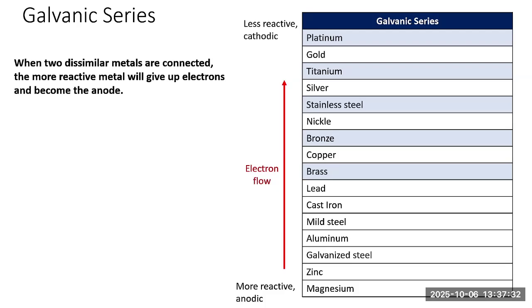And here's an example here, an aluminum fitting attached to a copper pipe. And I'm going to circle the aluminum here and the copper. So what do you think is going to happen here if I connect those two? Well, the aluminum is going to give up electrons and it's going to flow to the copper. So aluminum is going to deteriorate. If we look at a copper pipe connected to a bronze fitting here, now we have the copper becoming the anode and the bronze the cathode. Now, technically, electrons could flow from the copper to the bronze, but they're so close together, it's probably not going to be a significant problem here. So that's some of the concepts we can think about for galvanic corrosion.